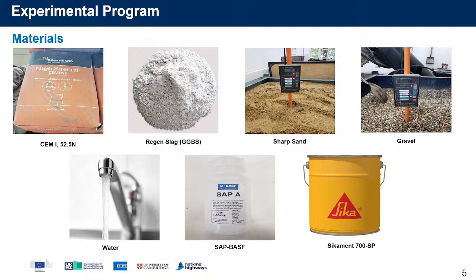In terms of the experimental program and the materials used in this study, Portland cement CEM I and the slag supplied by Hanson have been used as cementitious materials. Sharp sand and gravel with maximum aggregate sizes of 2 and 11 millimeters have been used as aggregate. I have used tap water for mixing the concrete, and SAP from BASF with a particle size of 100 micrometers has been used as a self-healing additive. And finally, Sikament 700 was used as a superplasticizer and water-reducing agent in the concrete mixes.